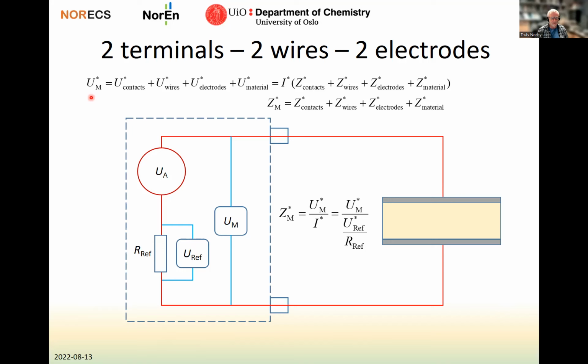The measured voltage here is now a sum of voltages. It is the voltage over the contacts here and here. It is the voltage over the wires. And then it is the voltage over the electrodes, and finally the voltage through the material. So this voltage is the current multiplied with the individual impedances of each source: the contacts, the wires, the electrodes, and the material. The current is the same going through all of them. There is the same current, but it has different voltages depending on the impedance in each term here.